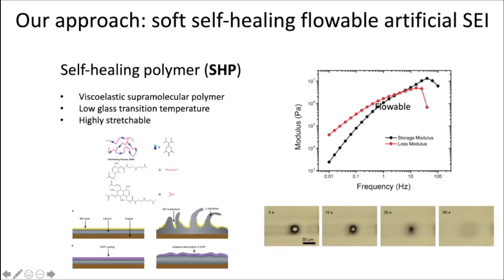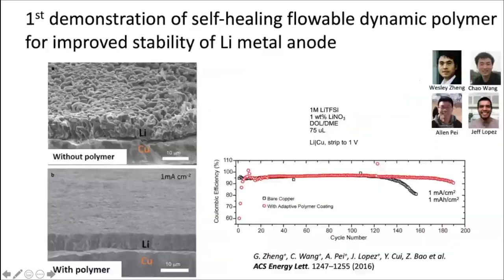And the other question we asked is, maybe if we have this kind of polymer that may provide more uniform ion transport, and there's no hotspot for ion transport, it might change the lithium metal deposition morphology altogether. So to our delight, we found that our first try actually got very exciting results: without polymer, we saw the typical dendrite growth, and with polymer, we saw a very dense and uniform layer of lithium metal grown on the surface. And indeed, it seems it's changing the morphology of the lithium deposition.